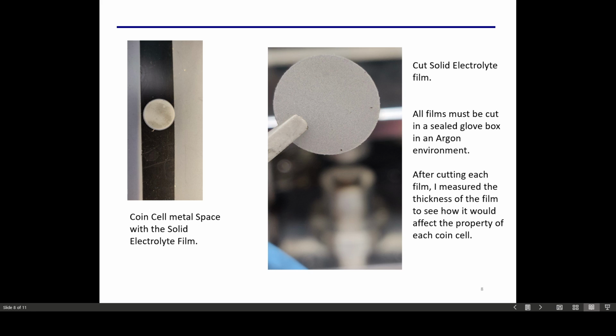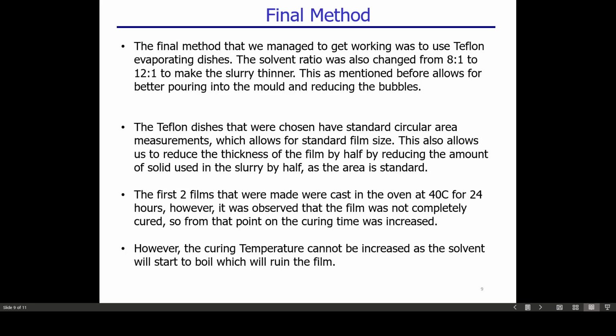Also, I measured the thickness of each cut disc to see how that would affect the properties of each coin cell. And the final method that we used to get really consistent films was to use something called Teflon evaporating dishes. The solvent ratio, as mentioned before, was changed from 8 to 1 to 12 to 1, where 8 to 1 is an 8 to 1 ratio of solvent to solids, to make the slurry thinner. This, as mentioned before, allows for easier pouring into the mold and also reduces the bubbles.